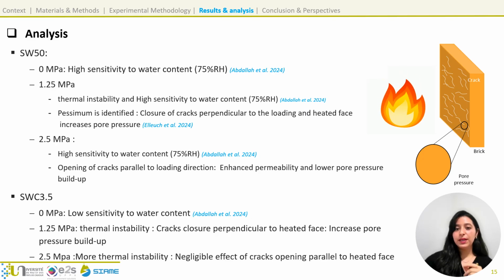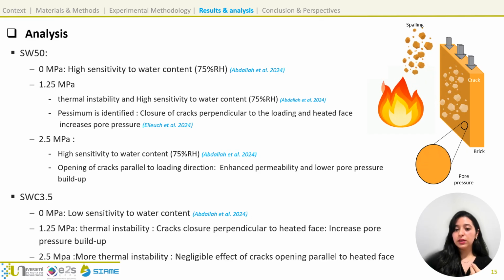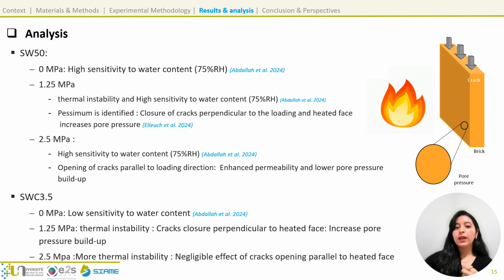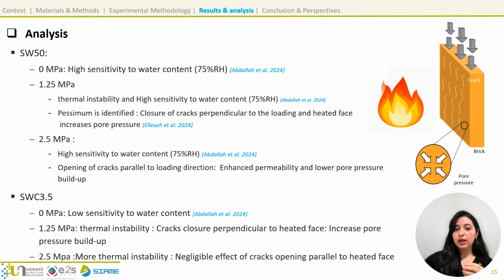To summarize this part, please pay attention to the animation. Here we have a brick, and generally the bricks contain small cracks in multiple directions. When a load is applied, some cracks perpendicular to the loading close, and combined with evaporation from the fire, pore pressure builds up, detaching layers and causing spalling. Then, as the load increases, cracks parallel to the loading open, allowing water to escape and lowering pore pressure, so reducing spalling.